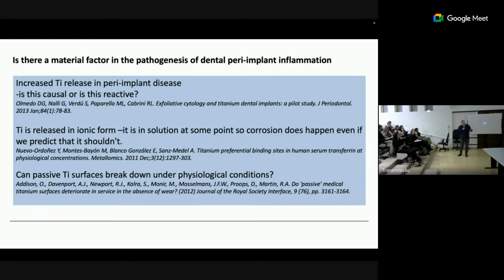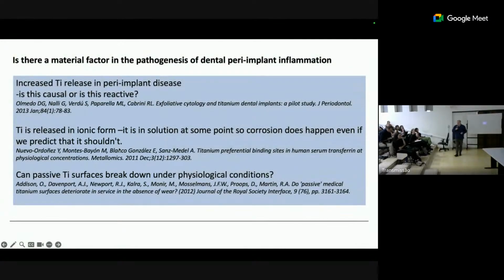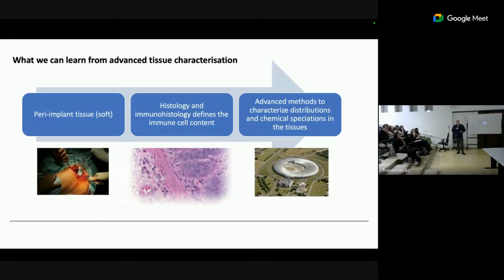But there were a couple of people at the time just throwing a few things out. And one of the most important ones was from the Montes Bayón group in Oviedo that did some beautiful mass spectrometry and demonstrated that in patients that had titanium prostheses, they had titanium bound to transferrin, which is your main chelator, or main carrier of iron. It keeps iron bound in extracellular fluids and in blood. They found titanium had displaced it, which means that at some point titanium had to get into ionic solution in order to end up on a protein. It's not a particle.